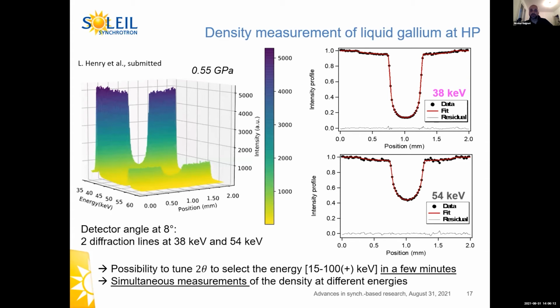It's possible to tune the detector angle to select the energy, and it's very easy. We can go from 15 to more than 100 keV in a few minutes. Just have to turn the detector. And we have simultaneous measurements of the density at different energies, which is also quite unique.